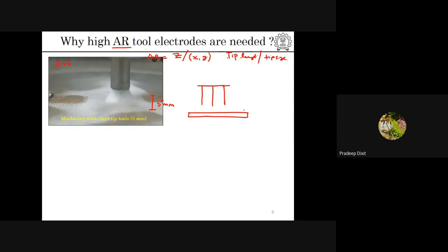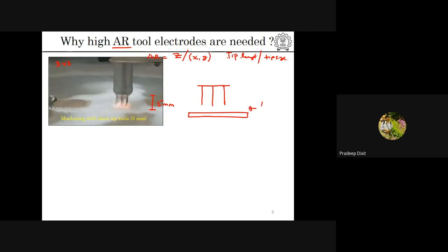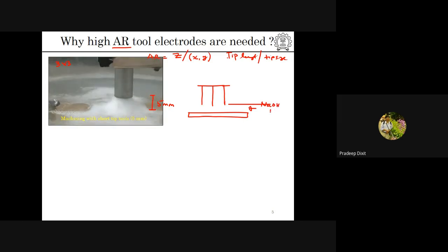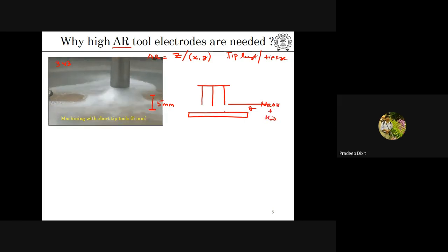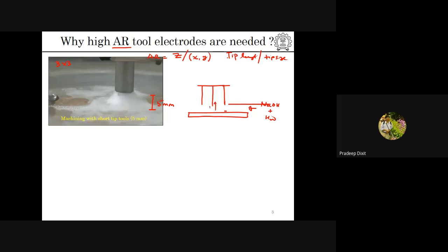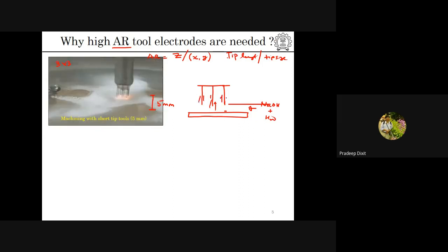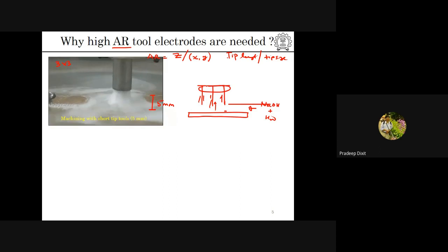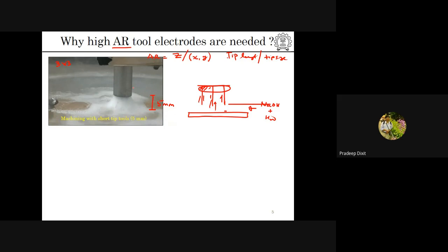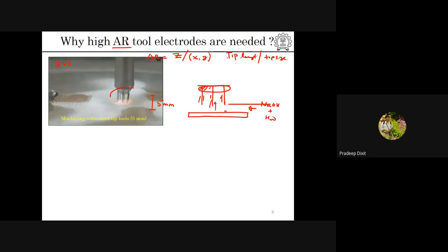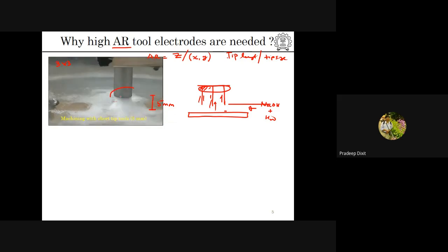What happens is that because of the high temperature produced in the ECDM process, here we have water, the electrolyte. If you recall, we mentioned that we are using an alkaline medium with water, right? So water vapor is formed, and these water vapors go like this. From each side the water vapor is going up, and here at this cold place they are forming this kind of bubble. If you look at this particular video here and focus on this side, you will find this kind of big bubble formation.